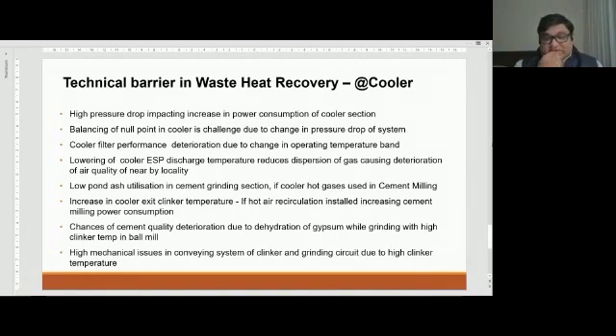But what happens on the other side of the process is that your clinker temperature goes up. But we have to take care of that. If your clinker temperature in the cooler is already lower, it is possible to do it. But if you're already running the clinker temperature higher, say about 140, 150 degrees, this has to be re-examined